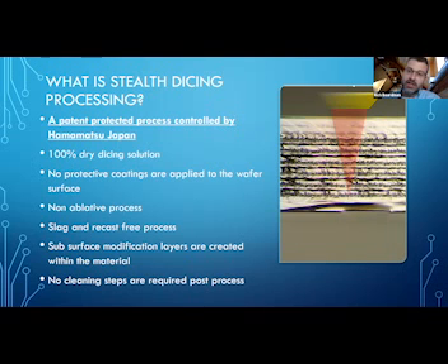So in essence, what we're doing, if you look at this sidewall image right here, we're using the top surface of the silicon as a secondary focusing lens for the laser. And then we're creating these modification layers beneath the surface. We'll typically start at the bottom, where you can see my cursor right now, and we'll build up. Depending on the thickness of the silicon will dictate how many modification passes we need to induce. And then once that laser modification process is complete, if you were to look at the wafer on the tool at that point, it would almost look as though nothing had happened.